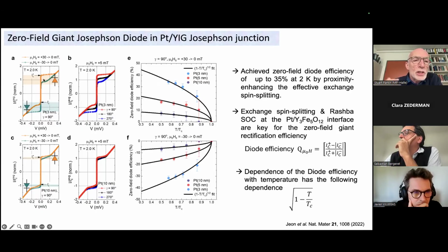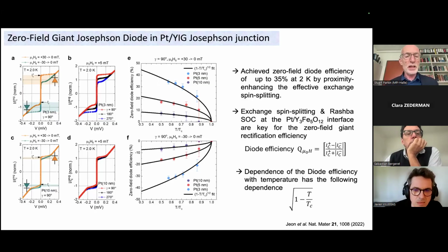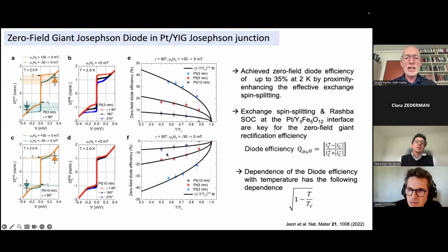However, if we now switch the magnetization of the YIG, so it's magnetized in the opposite direction, then we see the green curve, and now the critical current for the positive flowing direction is less than in the negative flowing direction. And by the way, this platinum here is only 3 nanometers thick. If the platinum is too thick, then the double proximity effects, the superconductivity and magnetism, will no longer interact. And in E, you can see this zero field diode efficiency and how it varies as a function of temperature for different thicknesses of platinum: 3, 5, and 10 nanometers.